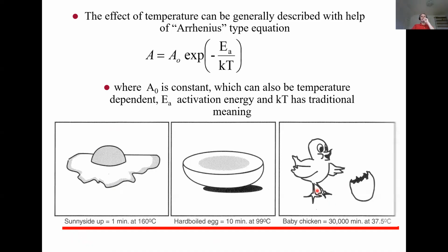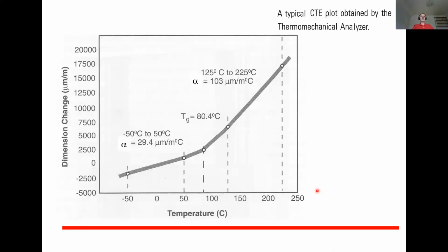The other thing is that we have a mechanism which is happening in a certain temperature range, but we also need to understand that some materials' properties as a function of temperature are not linear, or not even following some continuous curve, but have abrupt changes. And again, our organic materials are problematic in this respect. So here is an example of a typical epoxy. Epoxy is a material which we see very frequently, and not only in our normal everyday glues, like Araldite or whatever you purchase from K-Rauta, but also in our electronic products. For example, most of the organic substrates are more or less based on epoxies, different types of epoxies.